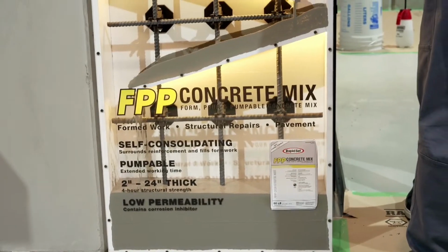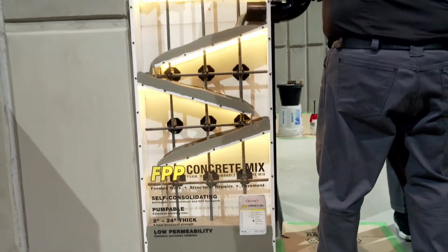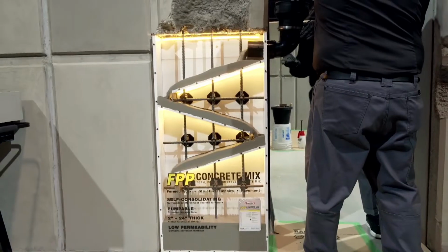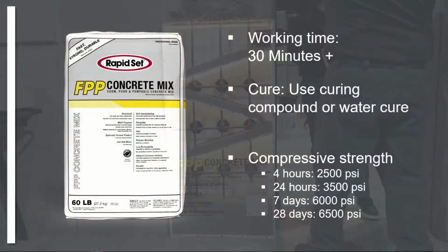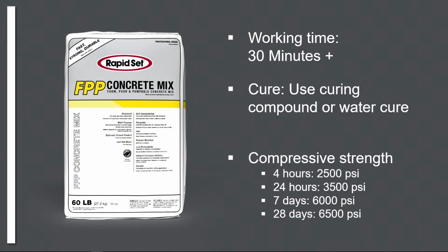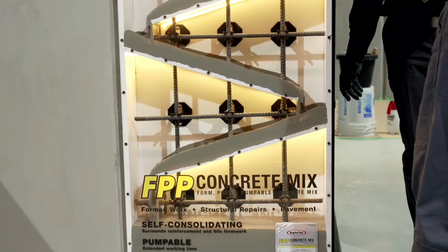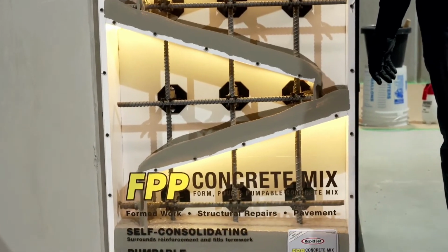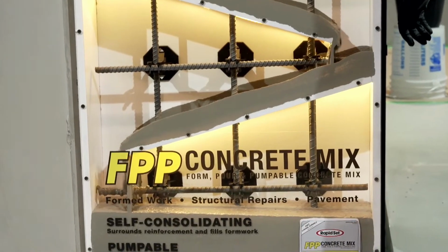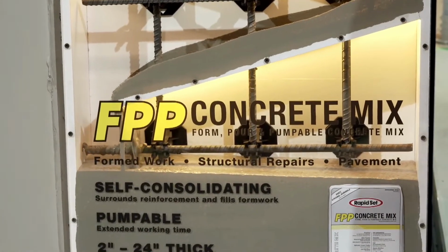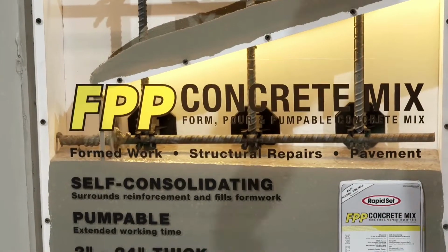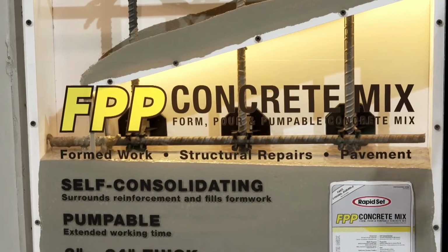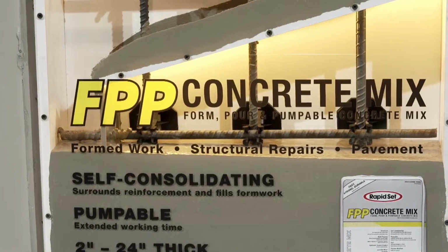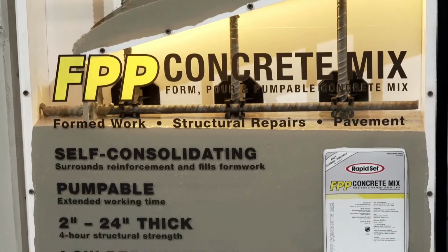This also contains integral corrosion inhibitor. So we have independent testing by ASTM C1202, which is a rapid chloride ion penetration test. And what that measures is the chloride ions penetrating through the concrete. And this one, by independent testing, we have very low permeability, which means the salts and the water have a hard time getting through the concrete to attack the rebar. And that's because it contains a corrosion inhibitor already mixed in. So this is designed to easily flow, encapsulate that rebar, and really provide that protection.